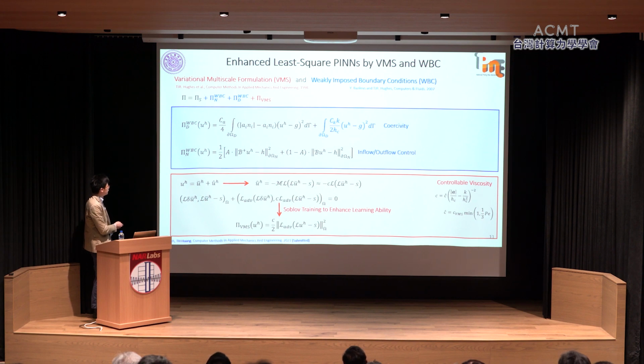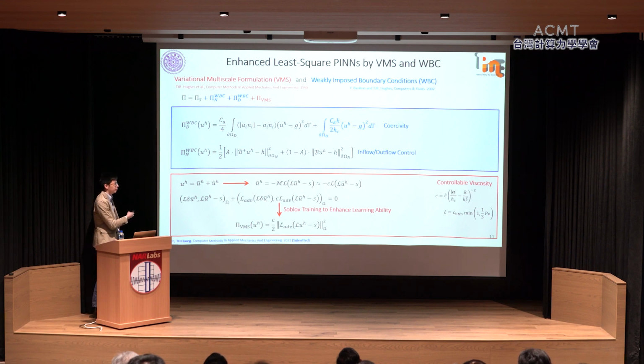You can see that this one comes from the least square loss of the momentum balance equation, and this gives you an additional term that looks like this, where LUh minus S is the strong form loss, and you take the advection operator on it. This is similar to the so-called Sobolev training, I think Sunwei Shin's recent paper in crystal plasticity to enhance the learning ability, or a more recent paper by Professor Karniadakis, the so-called gradient PINN, adding a gradient term. But their methods don't have a specific definition of this regularization parameter C. Here, because of this procedure, I can actually derive the form of C. And I only need C to be 10 to the power of -4 in the solution. That's enough for my purpose to model the problem.